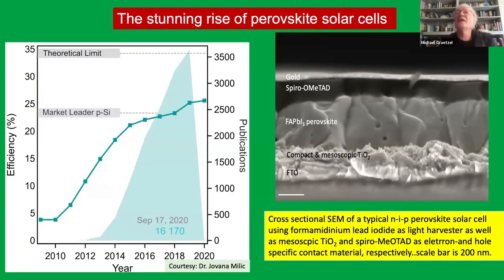If you have 2 selective contacts and you have a photoactive material with diffusion lengths of the carriers that must be at least as long as the light absorption length, which in the perovskite is about a half a micron. And the diffusion length of the carriers is several micrometers. So you can capture the carriers before they recombine. You don't need an electric field to separate them. It's very similar to dye-sensitized cells, where the carrier lifetimes are in the second domain, hundreds of milliseconds. So even though the diffusion is not very fast in the DSC, we can capture those carriers. In the perovskites, the diffusion is fast, and recombination is also faster than for dye-sensitized, but the product of diffusion coefficient and lifetime is large enough to ensure that you capture these charges.